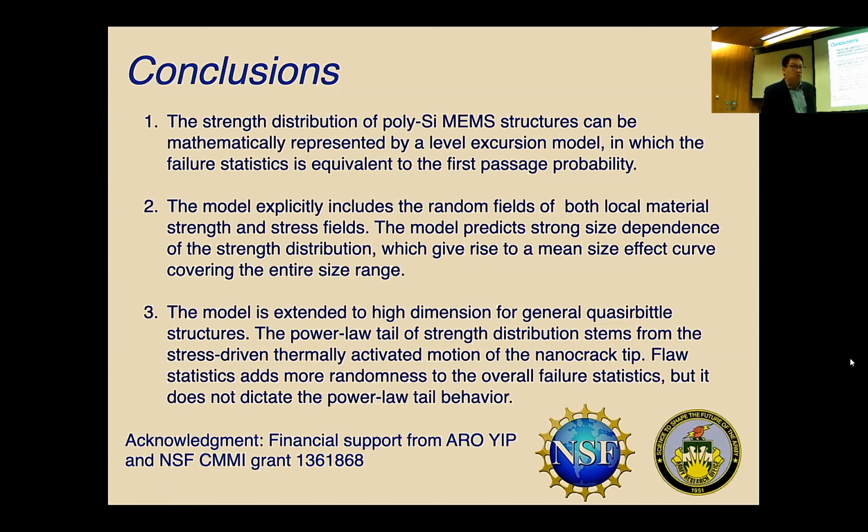Flaw statistics is important. Okay, it adds more randomness to the overall failure statistics, but it does not dictate the power law tail behavior. The form of the power law tail is not dictated by stress, but by the strength field.